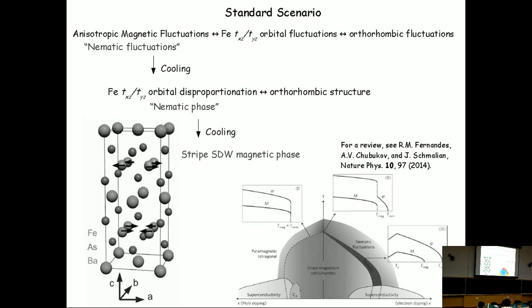So the standard scenario to describe what's going on here is that at sufficiently high temperature, you have a tetragonal phase with no magnetism and no anisotropic conduction. But on cooling, we start having what we call anisotropic magnetic fluctuations, where the magnetism is already trying to set up. And since the magnetism is a stripe magnetism, these magnetic fluctuations induce some kind of orbital fluctuations, some kind of differentiation, at least locally, between the XZ and YZ orbital occupations, because that selects some preferred direction to have the magnetic coupling more satisfied, and that's also connected with some orbital differentiation in the iron orbitals.